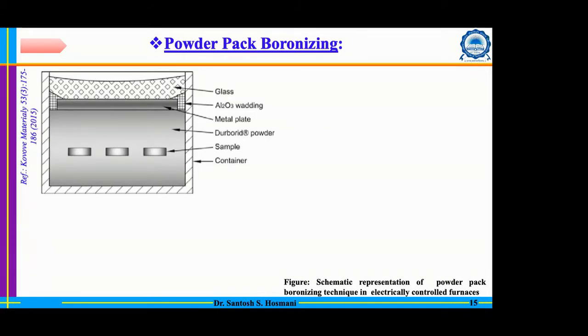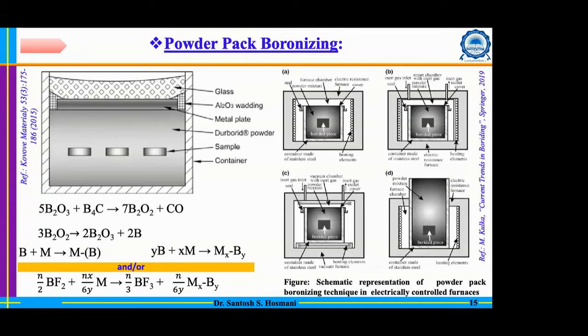The purpose is basically to avoid any kind of environmental contact with the boronizing mixture. Because the problem is that if you have oxygen trapped in this powder, that will lead to the formation of porosities at the specimen surface. That will again create a problem, especially during application, because if the porous layer is the top layer, either you have to remove that porous layer or you have to find a way to close those pores. If not, in principle that will be a disadvantage, because cracking can occur easily, especially in the top layer. So that's why people have used various combinations, and even in furnaces they have used an inert atmosphere. Probably the inert atmosphere will take care of eliminating the oxygen in the environment, and you can avoid the unwanted reactions there.